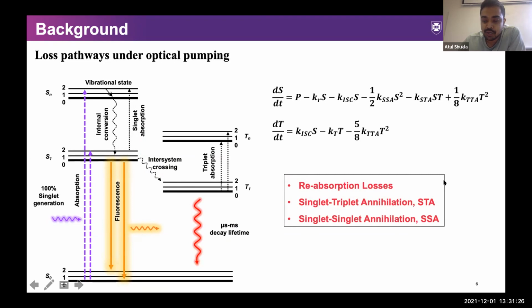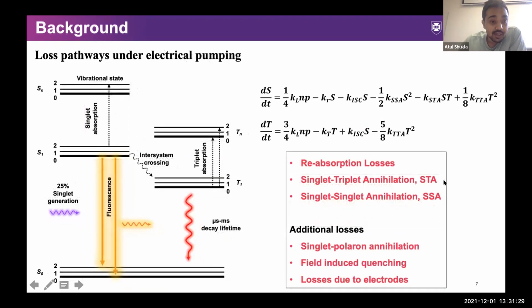but under nanosecond optical pumping, singlet triplet annihilation doesn't really play a major role. But when we move on to electrical pumping, we are handicapped firstly by the singlet generation yield, which is just 25%, and we have 75% triplet excitons, which have a very long lifetime. So not only is the population higher, they can also accumulate over time. The singlet triplet annihilation losses are extremely high, and there are also additional losses such as singlet polaron annihilation, field induced quenching, and losses due to electrodes. This makes electrical pumping a major concern and a big challenge for the community itself. And this is what we try to do: manage these triplet excitons so that we can get better performance of these materials.